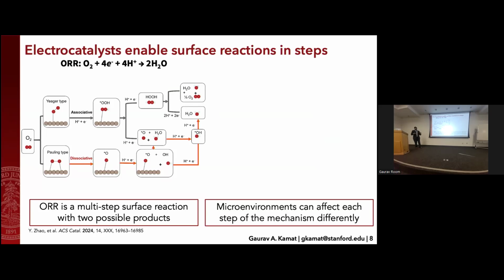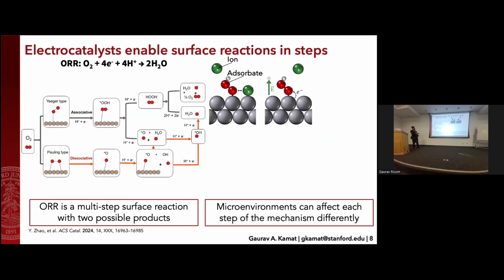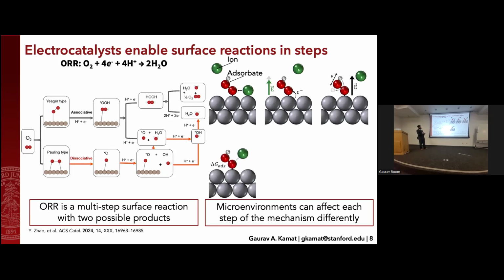Now, the microenvironment that I mentioned before can affect each of these steps in the mechanism differently. These are all happening at different relative energies and all happening at different rates. So as an example of that, you could have ionic adsorbates interfering with the adsorbate and competing for the same active site. You could have them inducing changes to the local electric field so that it's harder or easier to perform one set of that reaction. They can interact with the dipole moment of certain adsorbates and therefore change their energy of adsorption, or more directly chemically interact and change things like the transition state.